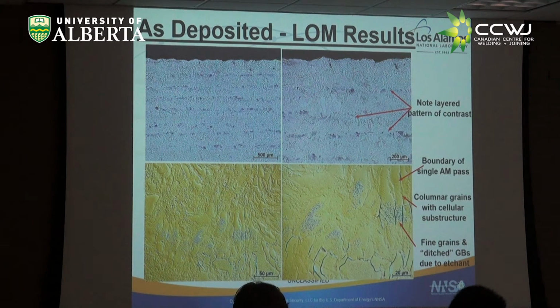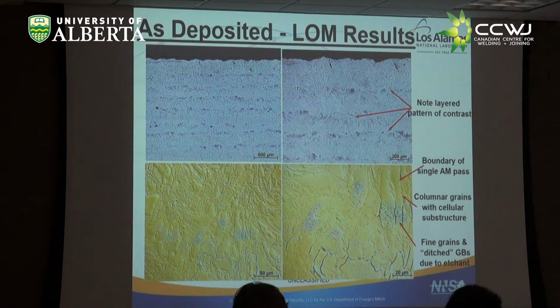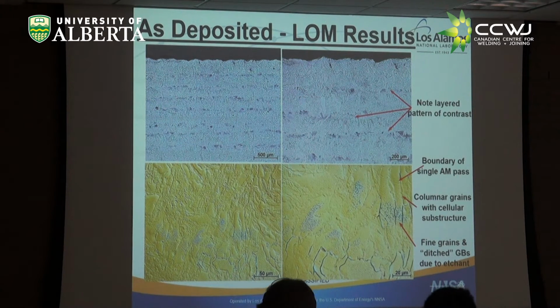You can see that there is this pattern of contrast, layered contrast here, some interesting things going on. The next slide is actually probably the most interesting one. We can see the different layers, and at the bottom of each layer there's this dark contrast. We can see here a solidification boundary of a single AM pass. In any given layer, we'll do bunches of passes, parallel to each other. The next layer will be put down at an angle of, I think, 67 degrees, so it never repeats, it just continues to cycle. And so it's difficult to interpret some of the microstructures here.